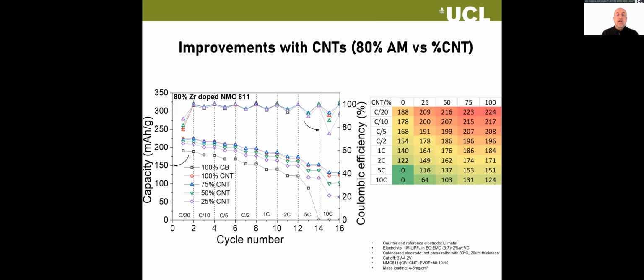One of the things we started to do was replace in our electrode, often you're working with 80 weight percent active, 10% binder, and 10% carbon black. One of the things we started to do with our cathode materials was to look at replacing them with conductive carbon nanotubes. So this is one of those experiments.